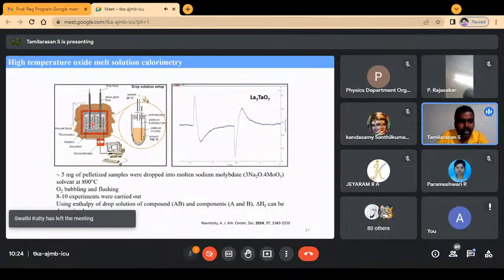Now, what happens here is you drop the sample in. The rest is like the sodium chloride in water analogy. It just dissolves, and when it dissolves, it either takes energy or releases energy, and we get this as a signal. This is my own compound, which has both exothermic and endothermic signals, because the endothermic part is due to the uptake of heat and then it dissolves slowly. So it has both steps, but a usual experiment will have only one step in one direction. So this is how we measure. If you want to measure the enthalpy of formation of a compound AB, you do drop solution with the same method. You drop and measure the drop solution of A and B separately, and of the compound AB. Now, when you do a thermochemical cycle, the excess or deficient energy is going to be the enthalpy of formation.